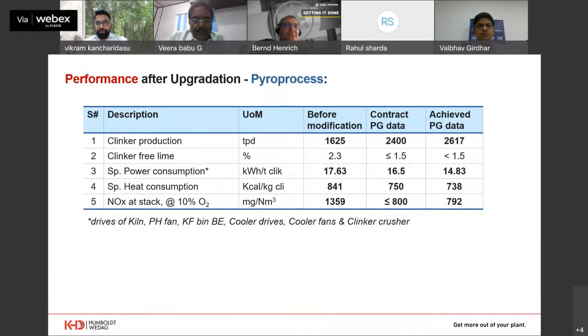And coming to the performance, the pyro process system, if you see, we have given certain guarantees during the contract signing time. All those guarantees are achieved. But when I compare this data with the before modification, these results are mind-boggling, seriously, because 1625 TPD has been increased to 2617. The specific power consumption for certain equipment, which I have given in the table below, 17.63 kilowatt hour per ton is reduced to 14.83.